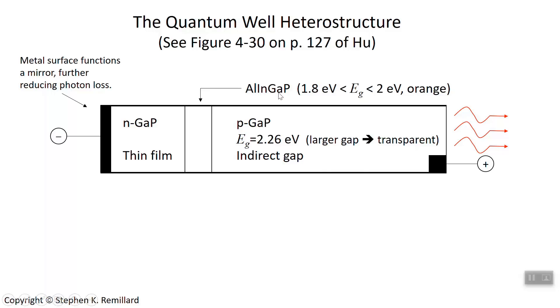Indium aluminum gallium phosphide has a smaller band gap, 1.82 electron volts, which is in the orange to red. The photons are generated in this region. That's where it happens. And they're in this region, and they have to get out the other end. So we have a little window over here for them to escape. And the gallium phosphide is transparent to those photons.